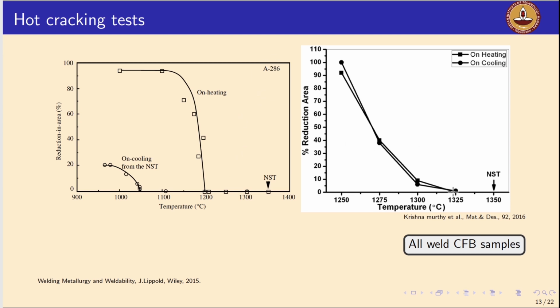But with the optimization of the chemistries, the candidate chemistries can be tuned such that the temperature range between the NDT, NST, DRT can be reduced significantly. So this is carried out in all-weld carbide-free bainite welds from one of our colleagues, and it clearly shows that by carefully modifying the chemistries, we can reduce the hot cracking susceptibility very well.